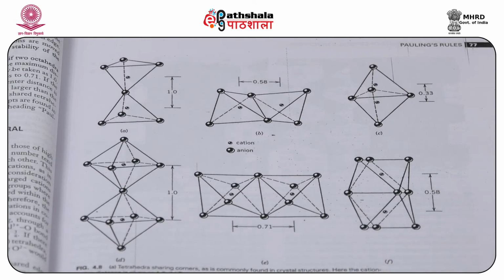This accounts for the lack of AlO4 structures and tetrahedra bonding, though bridging oxygen is found in many silicates. The Al3+ ion bonded to oxygen in tetrahedral coordination has an electrostatic valence of 3/4. If there was a bridging oxygen between two AlO4 tetrahedra, it would mean 2 × 3/4 equals 1.5, and the O2- charge would not be satisfied.